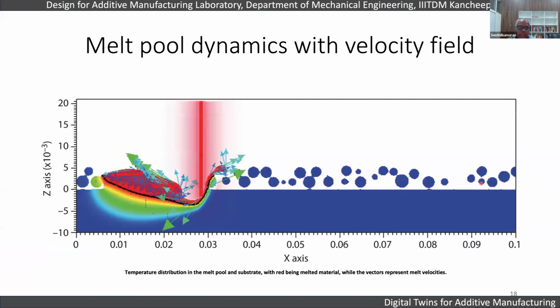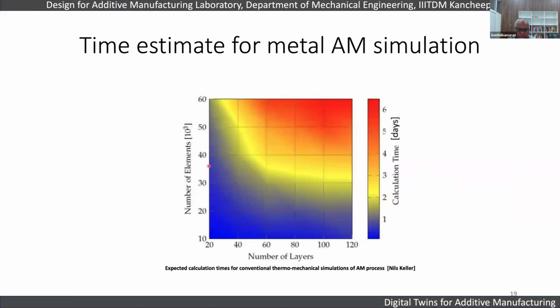So this is the melt pool dynamics shown along with the velocity field. You can see in the XZ plane, this is the temperature distribution on the molten fluid, the red melting material here. You can see, with the laser beam, how different particles get melted, and the melt zones and the temperature distributions, and the velocity profile of the melt zones are also shown. The velocity field is also shown.